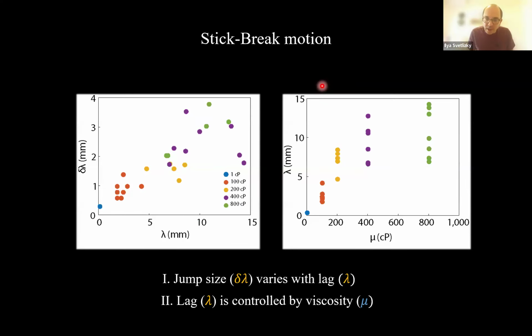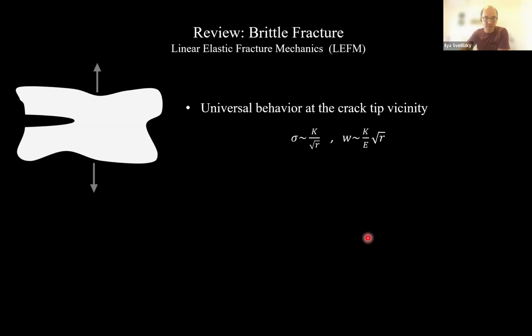Okay, so we can sum up all the measurements, different viscosities. The left figure plots the jump amplitude, delta lambda, versus the lag. As I said, the larger the lag, the larger the jump amplitude, and the lag grows with the fluid viscosity mu. These are the two results that I will start with, giving a very simple model to make sense of what you see on your screen.